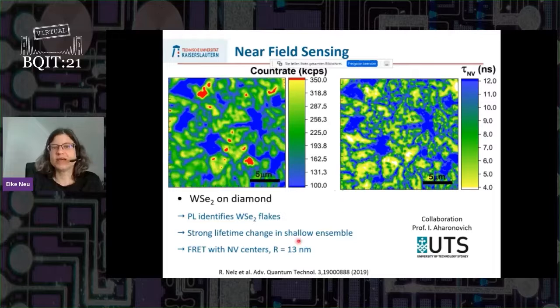And for the experts, we have calculated the so-called Förster radius of 13 nanometers, which is the point where the efficiency of the transfer is 50%. So it's a quite efficient transfer.